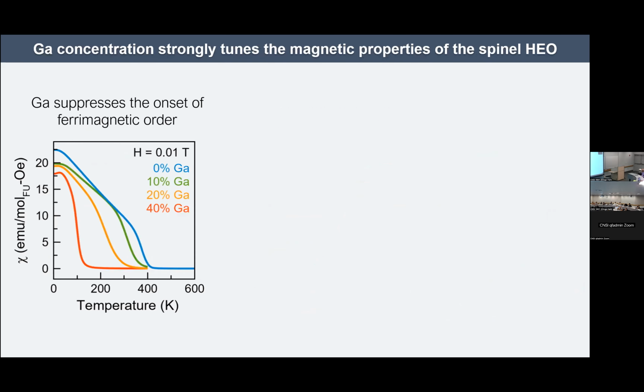Okay, so now we can look at what happens as a function of gallium substitution, where now we're going to systematically replace, again, in equal proportion. So my 5 transition metals are always going to stay in equal ratio, and I'm just adding in more and more gallium, 10, 20, and 40%. And if we look at the susceptibility as a function of temperature, we can see that there's a systematic suppression of the onset of magnetic order.